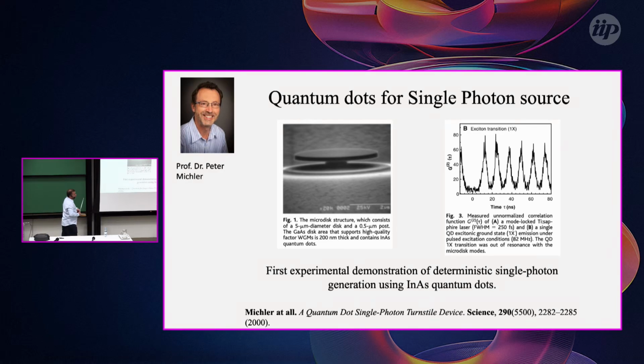Okay. The first demonstration of what people are now using indium arsenide quantum dots, or semiconductor quantum dots, for is to generate single photon sources. And the first one that demonstrated this, in 2000, as Jorge already showed, was Dr. Peter Michler, who is now in Munich. Basically, what the group of Michler did was embed indium arsenide quantum dots inside these microdisks, and they demonstrated that these indium arsenide quantum dots can generate deterministic photons. Here is the correlation image. I will explain more about this in the next slide.